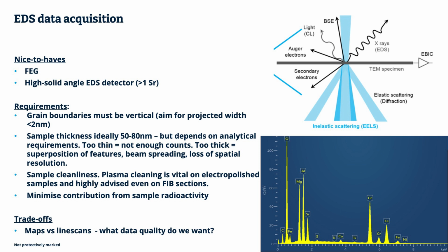And that's still a feature. I mean, despite the advances in electronics and online processing, if you haven't got the pulse pileup correction switched on, you will be seeing those peaks really prominently. And even if you have, sometimes it doesn't do a great job if the count rates are too high. It's not terribly likely in TEMs, but certainly in SEM applications, it's a pretty big problem.